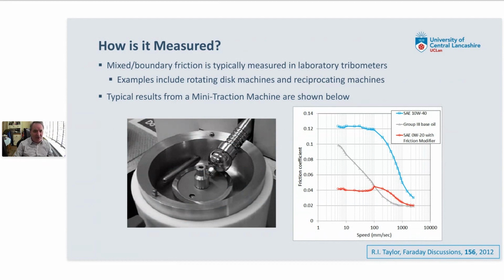So the wide range of disc speed that can be used in this machine means that you can go from boundary friction right through mixed friction almost to hydrodynamic, depending on the temperature of the oil. And what we can do is we change the ball and the disc for each test. The disc and ball are usually quite smooth. The surface roughness is about a few nanometers, 5 nanometers for the typical samples used here. And we can simply test different lubricants to see what the effect of changing the lubricant is on the friction coefficient.